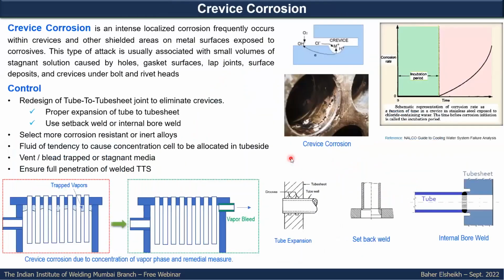The most common for the tube to tube sheet joint, first we will start with crevice corrosion, and here there is an example of crevice corrosion from the back side of the tube, where you can see the full tube thickness has gone, and you can see the leak directly there. And for crevice corrosion, as per this curve we get from the NALCO guide to cooling water systems, there is some incubation period for the crevice corrosion, and after some time, which in many cases might be one year more or less, then you will have some exponential acceleration rate for the corrosion attack.